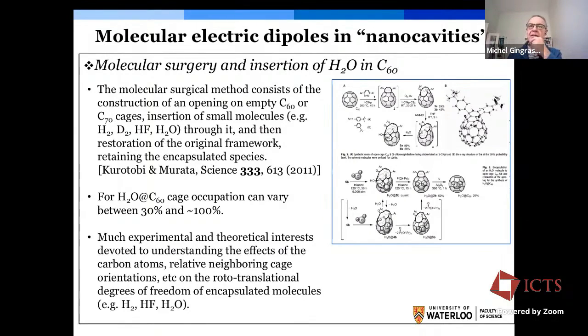And so small molecules that have been inserted in the C60 molecules are molecular hydrogen, deuterium, hydrogen fluoride a few years ago, water, and also heavy water. And what is phenomenal about this procedure, which has now actually crossed over to physicists who are making use of these techniques, is that the attack of the C60 molecule not only opens the molecules or the cages, allowing the small molecules to enter, but at the end of the chain of reactions, those C60 cages can actually be restored to their original structure, and the cages close, encapsulating the host, the water molecules, for example.